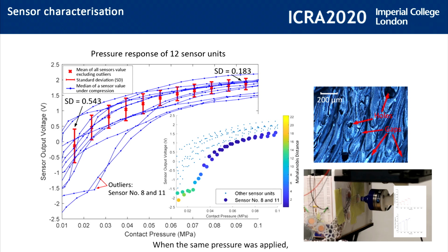When the same pressure was applied, deformations of conductive layers were slightly different, as the Young's modulus were different due to variance of porosity. However, when contact pressure increased, voids were squeezed and the microstructure of different conductive layers became similar, leading to smaller standard deviation. 10 out of 12 sensor units showed identical pressure response, indicating the reliability of the fabrication process.